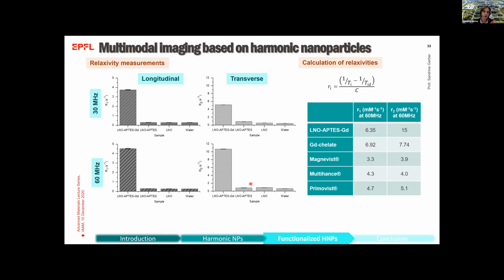So we have a covalent conjugation of those gadolinium chelates on the coated surface of the nanoparticles. Then we analyzed the relaxation time and rate of those nanoparticles, and you can see an increase of the relaxation rates of water protons, both longitudinal and transverse, at 30 and 60 megahertz, while the non-functionalized nanoparticle has no effect. After calculation of the relaxivities, you can see that with the functionalized nanoparticles we are in the range of the commercial contrast agent based on gadolinium chelates.